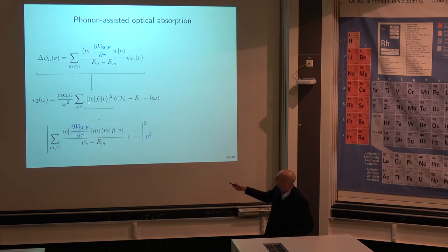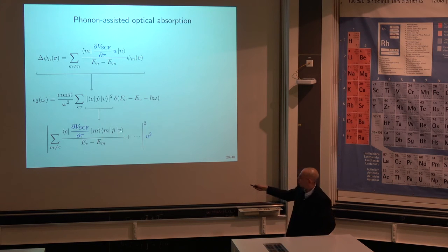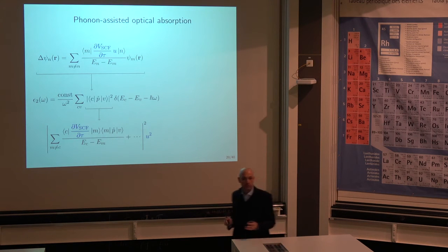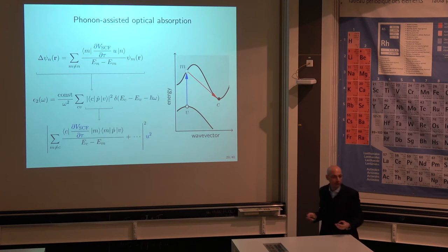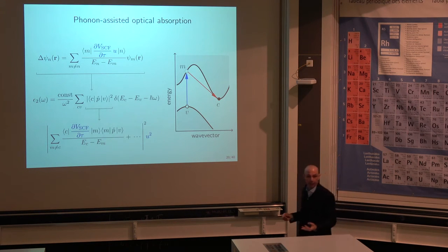There will be an electron-photon matrix element, this one, times an electron-phonon matrix element, this one. So you start from a valence state, you go to an intermediate state, then from the intermediate state you go to the conduction state. This should remind you of what you've probably seen in every textbook on semiconductor physics, what we call phonon-assisted optical absorption. So this essentially means that you can go from a state in the valence to a state in the conduction across an indirect bandgap if you have phonons there to help you, okay?